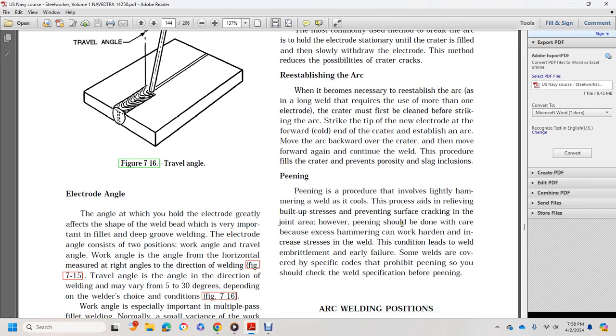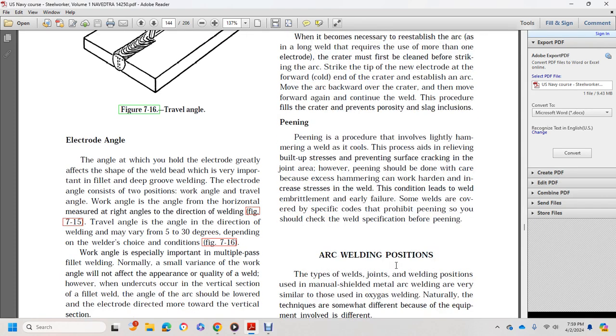Peening. Peening is a procedure involving light hammering of the weld as it cools. The process aids in relieving built-up stress and prevents surface cracks in the joint area. However, peening should be done with care because excess hammering can work-harden the metal and increase stress in the weld. The condition leads to weld embrittlement and early failure. Some welds are covered by specific codes that prohibit peening, so you should check the welding specification before peening.